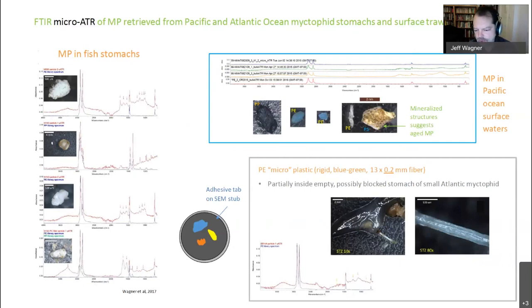Also, another example is on the lower right, you see a fairly large polyethylene plastic fiber, which since we didn't destroy the stomach, we could see was actually stuck in the opening of the stomach. Due to the nature of fibers having a very long aspect ratio, it was able to get in, but apparently not get out. And the stomach actually was one of the only ones we found that was completely empty of other material. Could be a coincidence, or perhaps it did block the stomach of this fish. So that was interesting information to find in this sample.